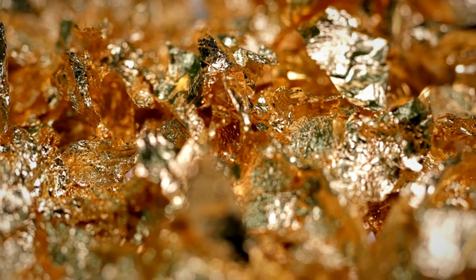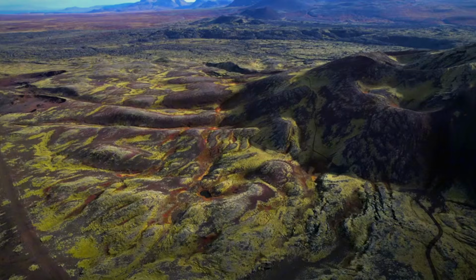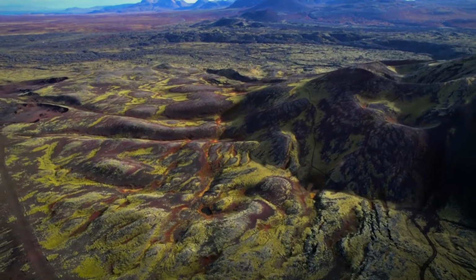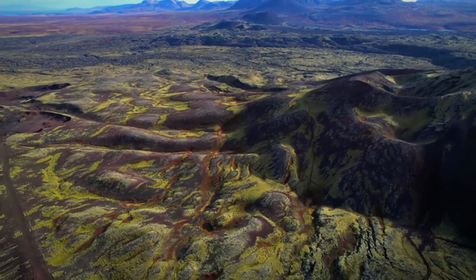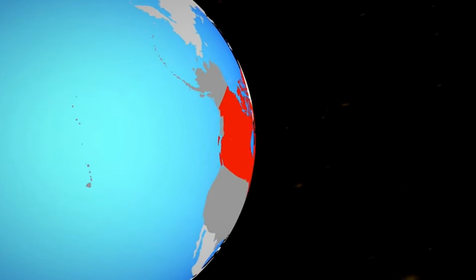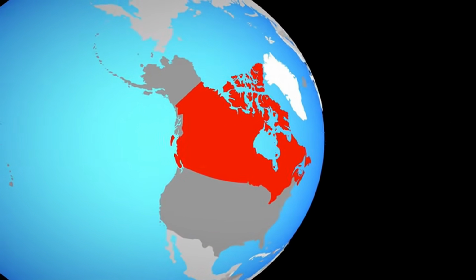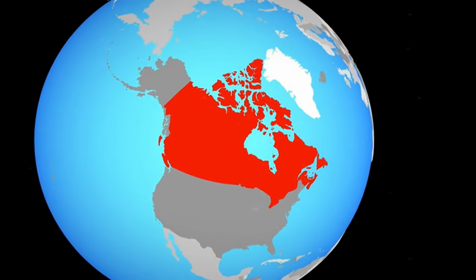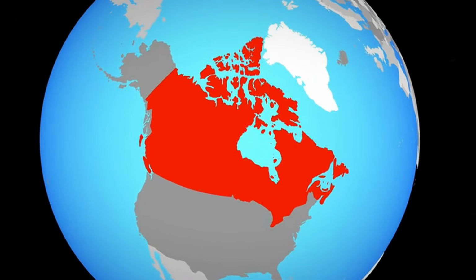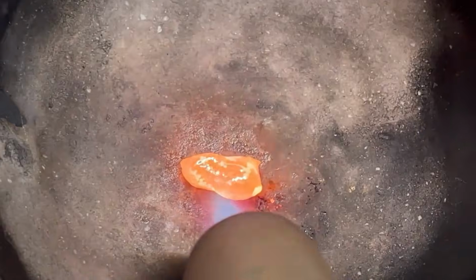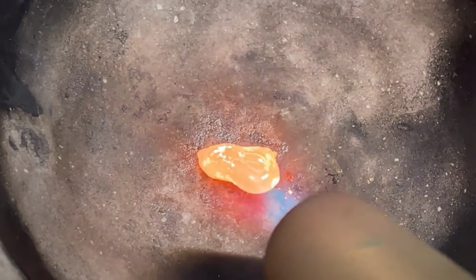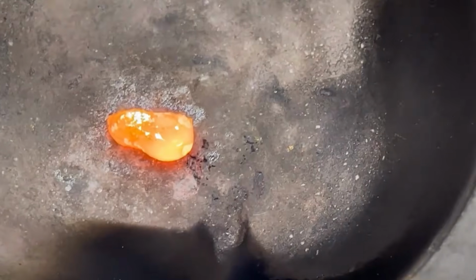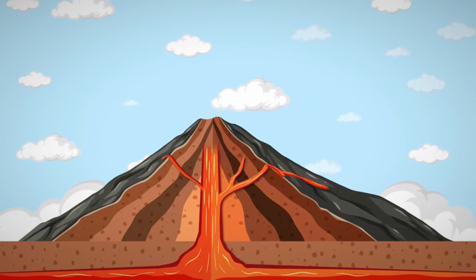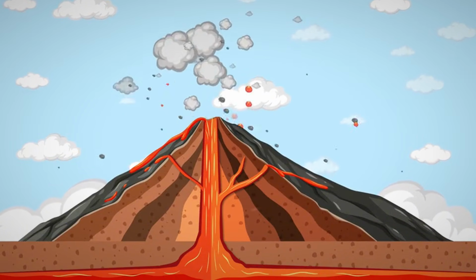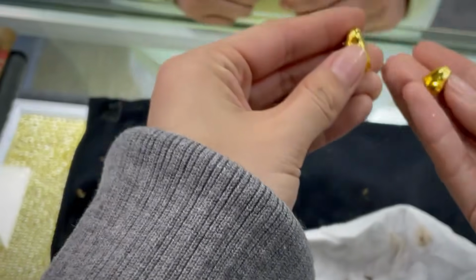If the source is gravity concentrate or leach precipitate, you'll first mix it with a flux, typically a blend of borax, soda ash, silica, and lead oxide, litharge. This flux lowers the melting point of the sample, collects base metals, and separates impurities into a glassy slag. The critical step is fusing the mix in a crucible inside a furnace, usually at 1,000 to 1,100 degrees Celsius. As the material melts, two things happen. Precious metals bind to the lead, which acts as a collector, and everything else either floats as slag or is left behind.